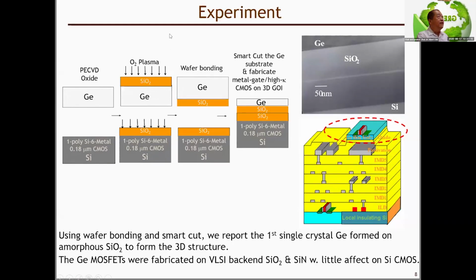So actually, we made the first 3D IC as early as 2004 using wafer bonding and smart cut technology. We made single crystal germanium on amorphous silicon dioxide to form the 3D structure. The germanium transistors were fabricated on the VLSI backend, the silicon dioxide or the silicon nitride, with little effect on the bottom silicon CMOS because the temperature of germanium CMOS is significantly lower than silicon.